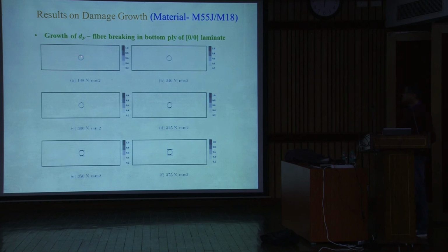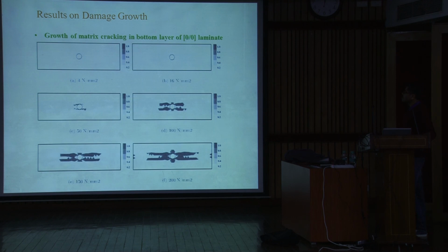So it starts at this location of this hole, and as your load progresses, you see that this fiber failure is only in this limited region. Okay, so we have not gone to the level of a complete failure of this plate. So this is the matrix cracking in the 0-0 laminate bottom layer.